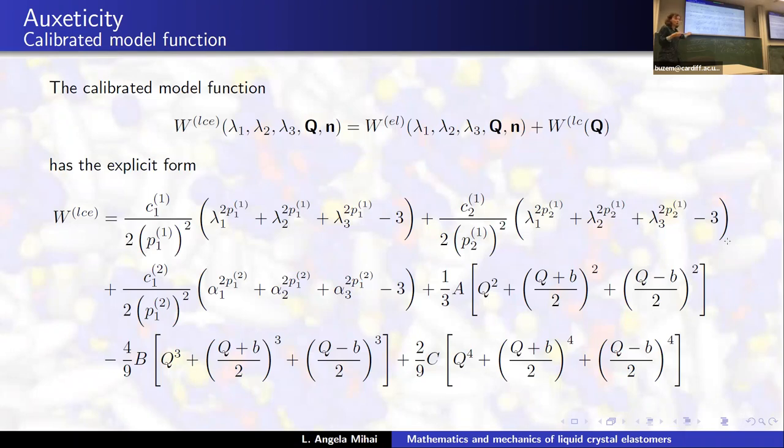It will be a function that will obviously exhibit this kind of deformation as an instability. So the normal deformation where you stretch and the material narrows in the other direction will still be a possibility from that material, but the other version is also possible. This is why I classified it under instabilities: this kind of deformation does not last very long. So it's unstable, but still it's observed. So it's still possible, and if it's possible, then it can probably be utilized in some way in applications, especially because molecular auxetic materials have not been known before.